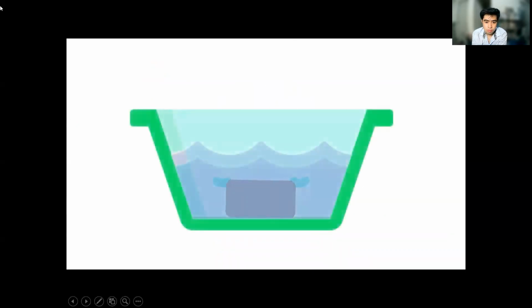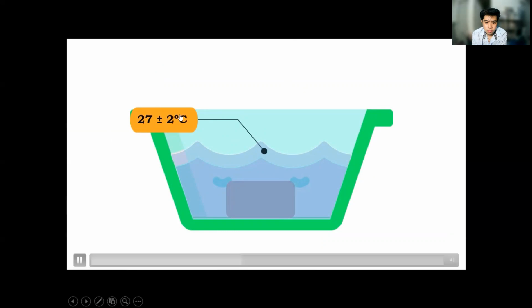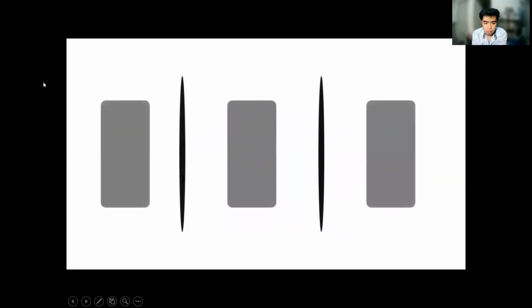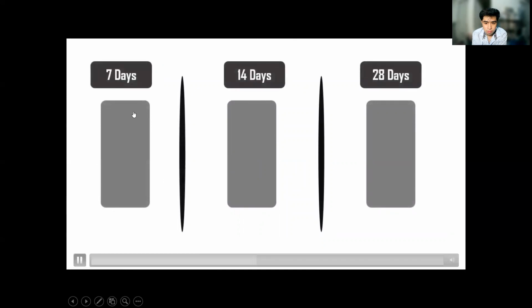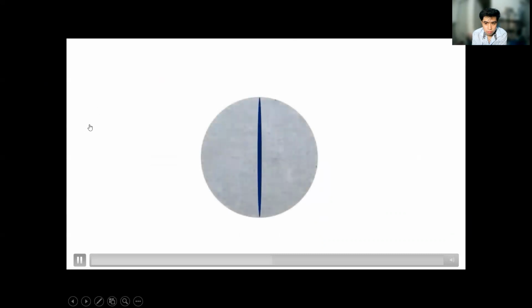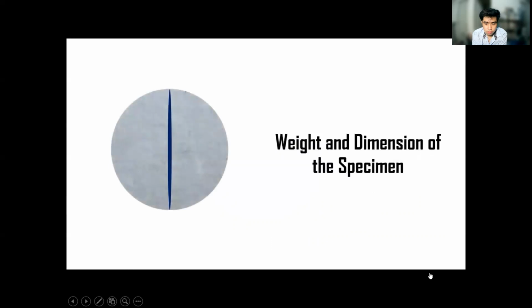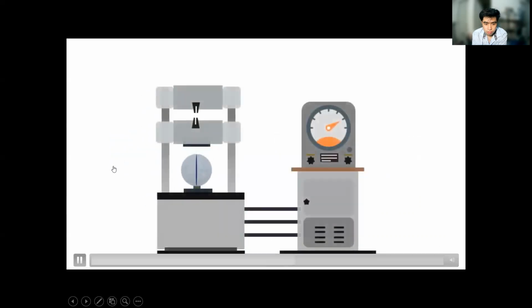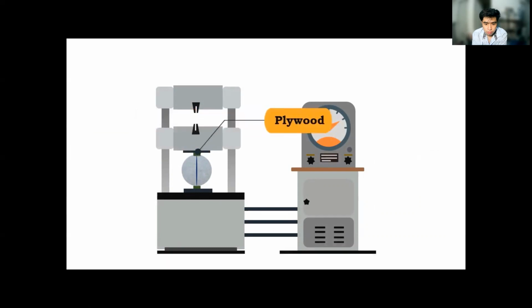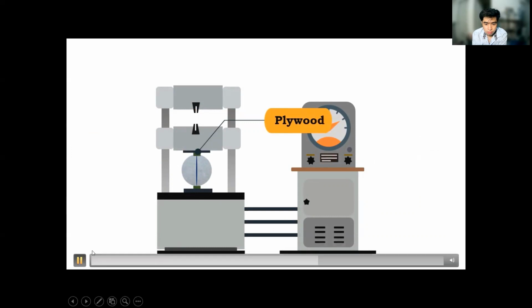After a day, the mold is removed, and the specimen is placed in the curing tank at a temperature of 27 plus or minus 2 degrees Celsius. Depending upon the requirement, the test specimen is removed from the tank and dried at 7, 14 and 28 days for testing. Draw the line on the specimens as displayed on the screen. Then, record the weight and dimension of the specimen. The specimen is placed longitudinally in the machine. A bearing strip made of plywood is placed on both sides of the specimen and aligned according to the marking.